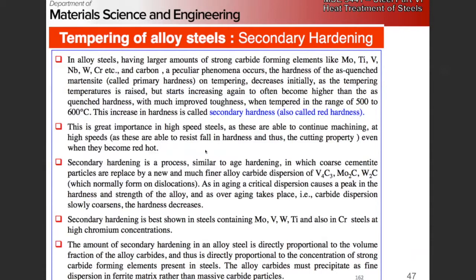Okay, so if we have our strong carbide formers as before, this is just some notes essentially re-saying what I had just said before, but it lists what particular carbides you're going to get. You get a lot of a mix depending on the concentrations. You can have a mix of homogeneous versus heterogeneous nucleation, right? Heterogeneous nucleation in this case is going to be mostly happening on dislocation structures, right?